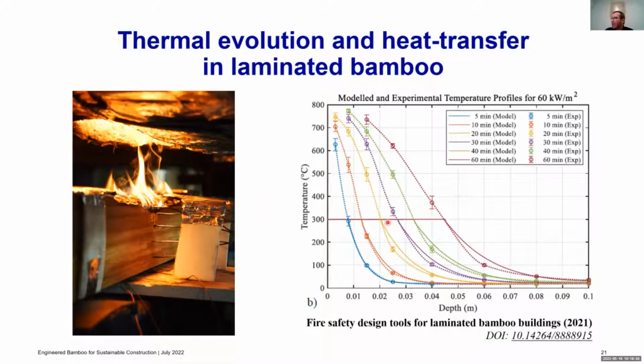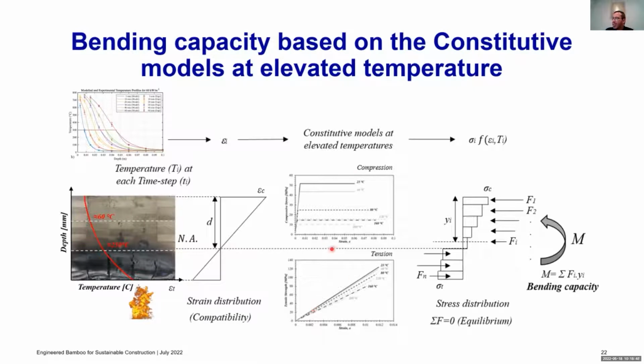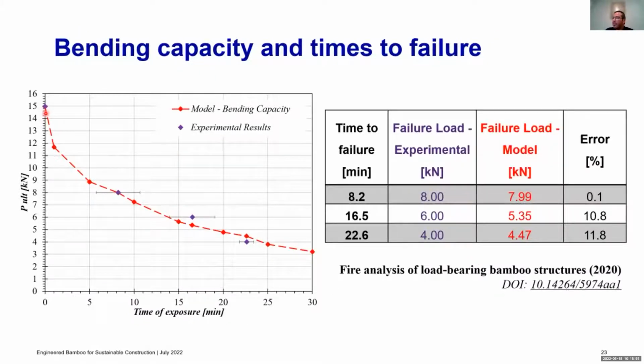Again, with that information, we calculated the temperature profiles. And with the temperature profiles and the constitutive stress-strain models, I developed a method to calculate the structural capacity. What you see here is that in purple, you see the experimental results of those tests, where I have the failure load on the y-axis and the time of exposure on the x-axis. So you can see how the material starts losing capacity over time. And in red, you see the model that I developed. What we observe is that the model and the experimental results have a really good fit. So we were very happy with the methodology that we developed to predict the capacity of those elements.